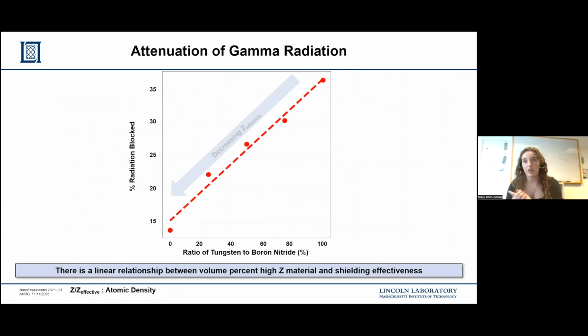So what we also wanted to study is how the ratio of tungsten to boron nitride affected the percent radiation that our shields blocked. This is, remember, our blended graded shields going from 100% boron nitride to 100% tungsten. And as you can see, there is a linear relationship between the percentage of the radiation blocked and how much tungsten is present in the system. So the more tungsten in the nanoparticle filler, the more radiation that we blocked with the same thickness shield.